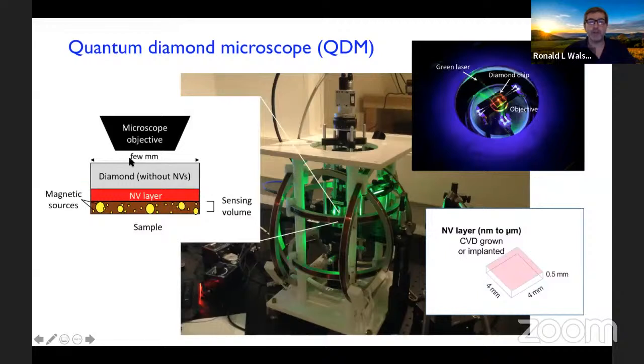This shows you a side view. So the diamond here is essentially the same diamond I'm showing over here. The bulk of the diamond has no NVs in it. It's just a substrate. It's just useful to have that diamond there as an object to be able to control it and place it onto the sample of interest. The NV layer, shown in red, and then some sample that maybe has magnetic signal sources. It could be wires carrying currents. It could be magnetization in some sample. It could be a biological sample. And there's a certain sensing volume you're probing over.